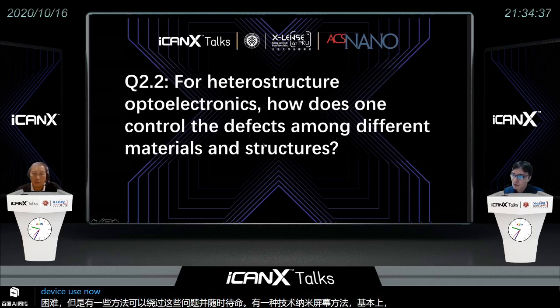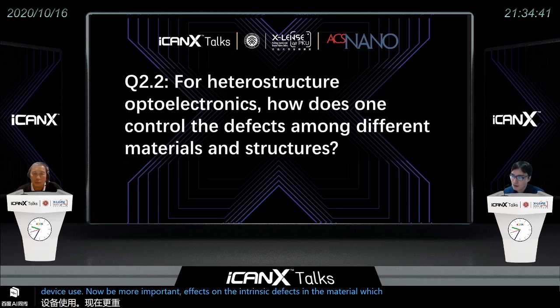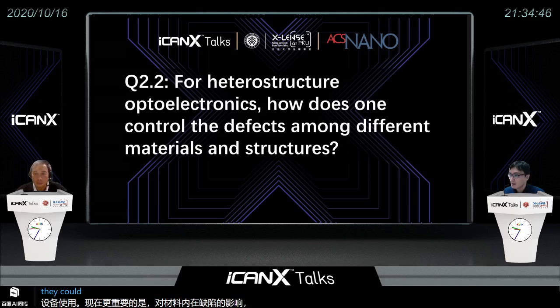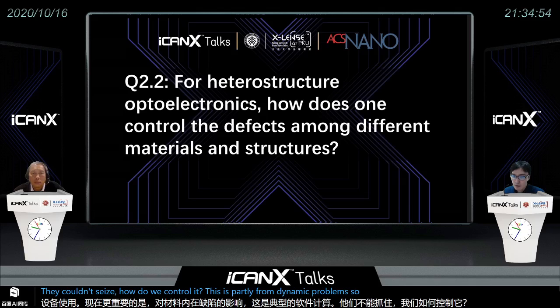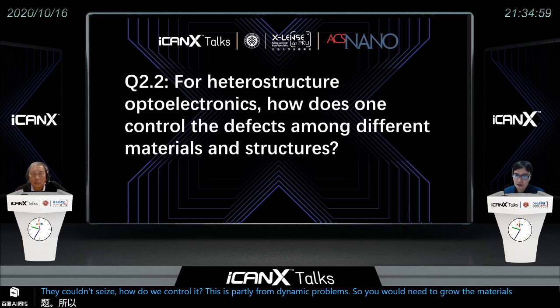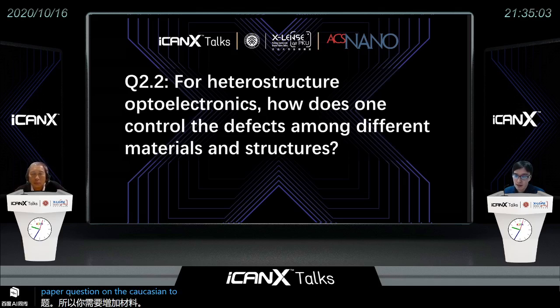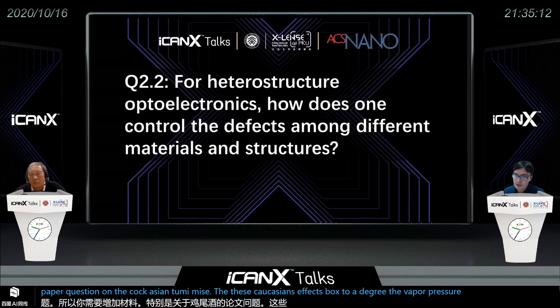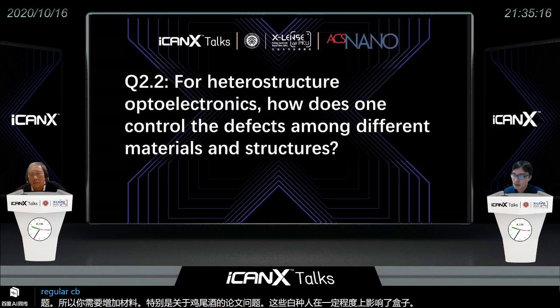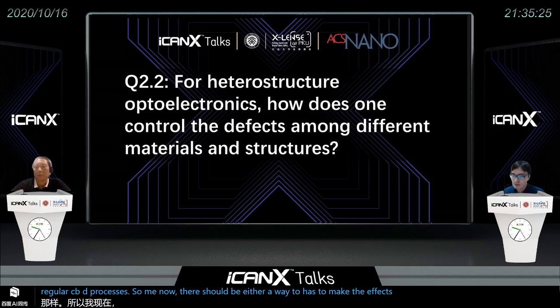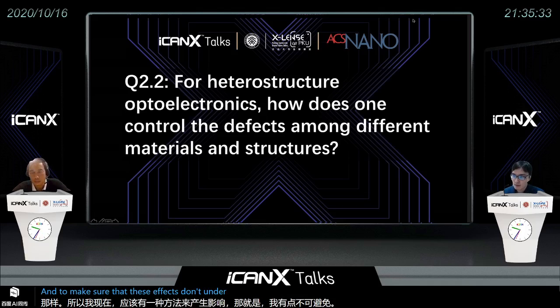Now, probably more important are the intrinsic defects in the material, which are typically sulfur or other chalcogen vacancies. How do we control them? This is partly a thermodynamic problem. You would need to grow these materials at a particular vapor pressure of the chalcogen to minimize these chalcogen defects. But typically, these vapor pressures are difficult to achieve, for instance, in regular CVD processes. So there should be a way to passivate these defects, which are somewhat unavoidable, and to make sure that they don't compromise the properties that you want to achieve.